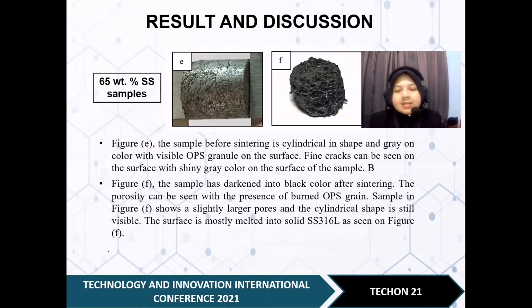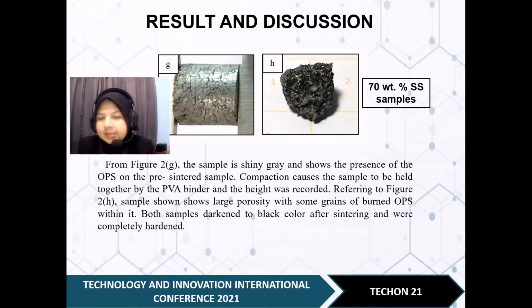The shape is still visible but it's not as perfect as the previous sample. The surface is mostly melted into solid stainless steel, as we can see in the figure. The next sample is 70% stainless steel content in the mixture. Same as the previous samples, before sintering the sample is cracked and the color is gray due to the stainless steel powder color. After sintering, it's hard to see the cylindrical shape because the stainless steel weight percent is increasing.